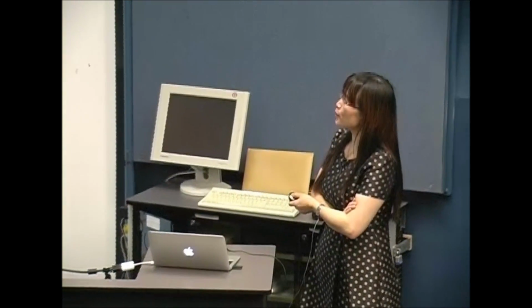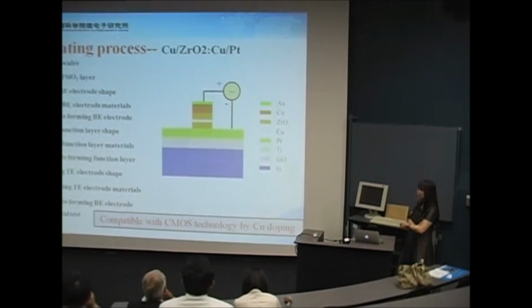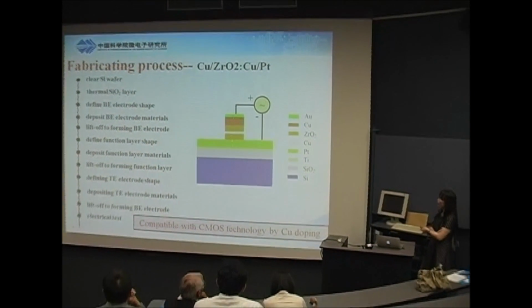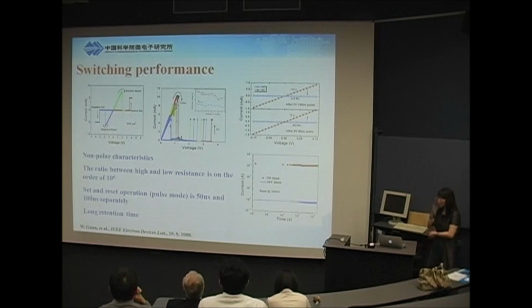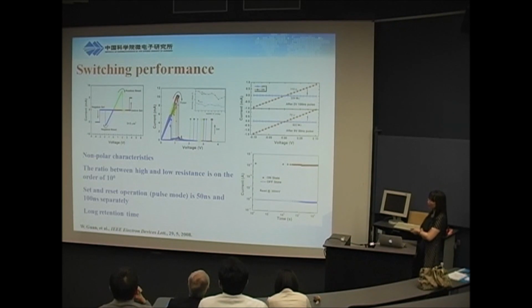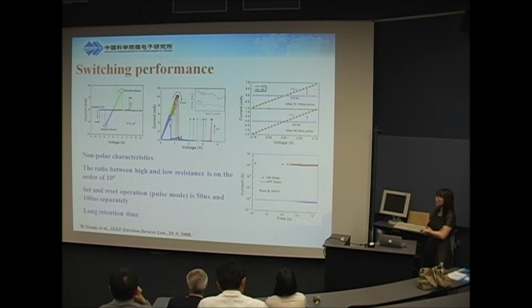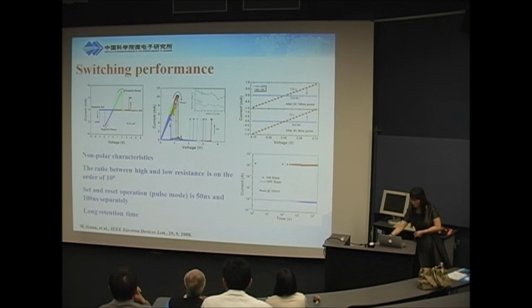For the fabrication, the device is very simple. We just use a fully commercial process compatible with CMOS technology. This is the device structure. So this is the performance of the device. We can see this device has no polarity characteristic, that means that both positive and negative electric fields can trigger the set and reset processes. We also see a very large ratio between the high resistance state and low resistance state, which means they have potential for multiple-level applications. Also very fast speed: we can reach 50 nanoseconds for the set process and 100 nanoseconds for the reset process. We also demonstrated a long retention time. So this is the basic performance of this device.